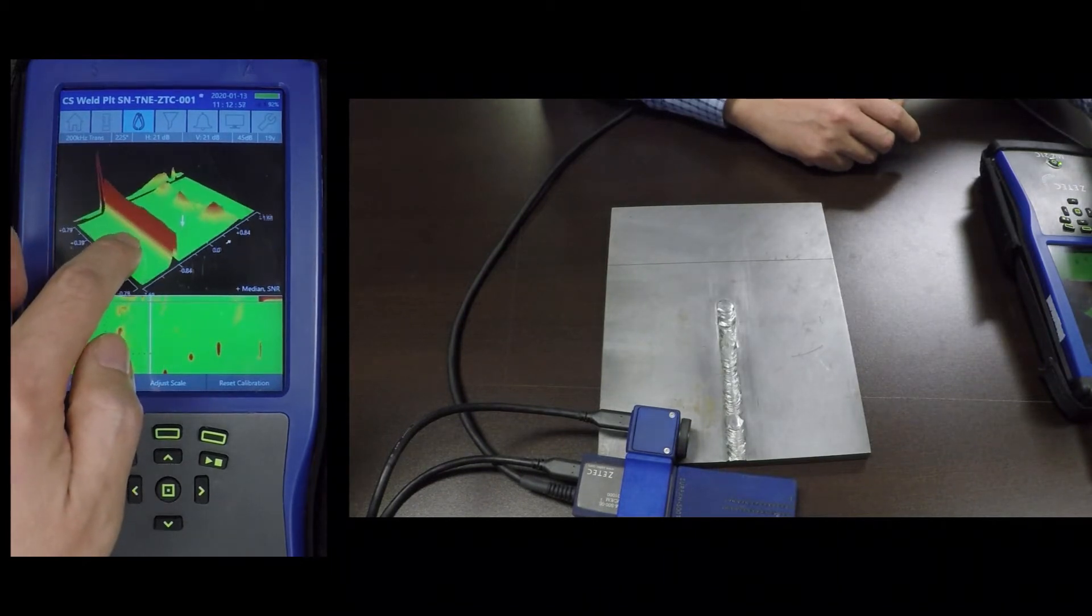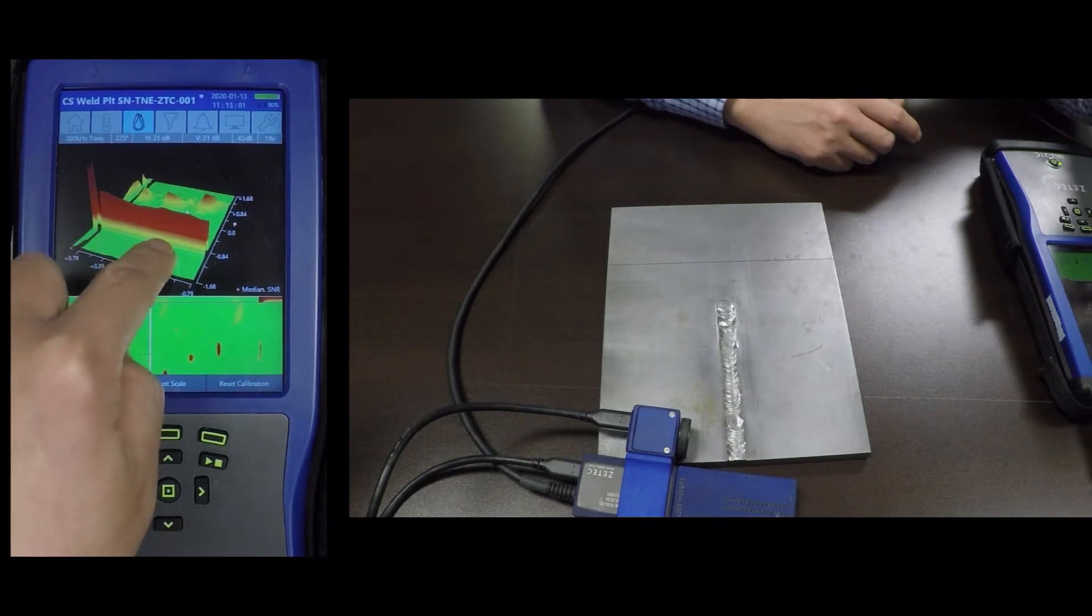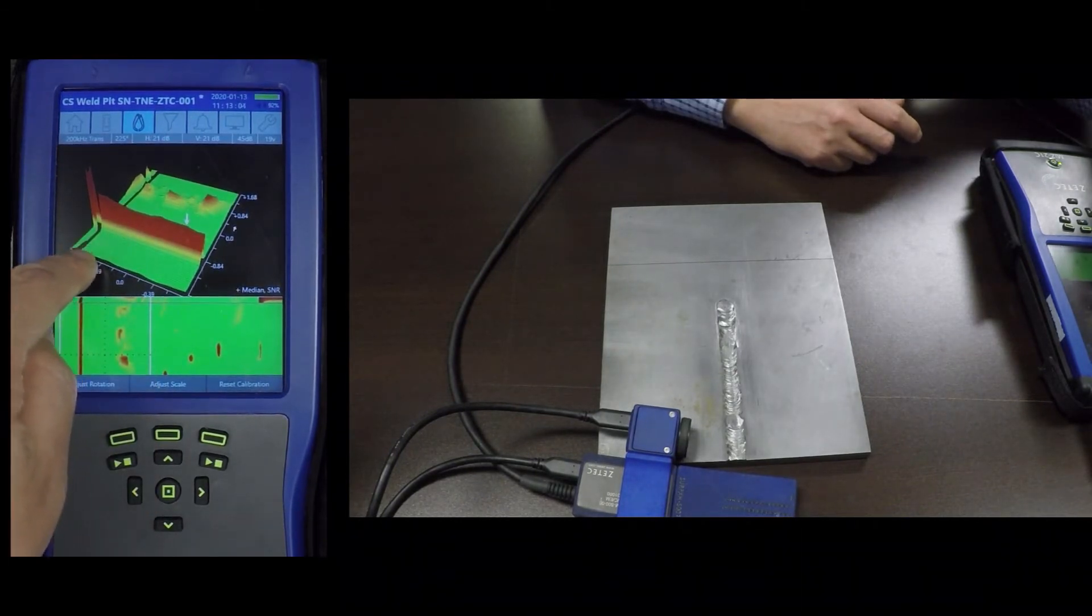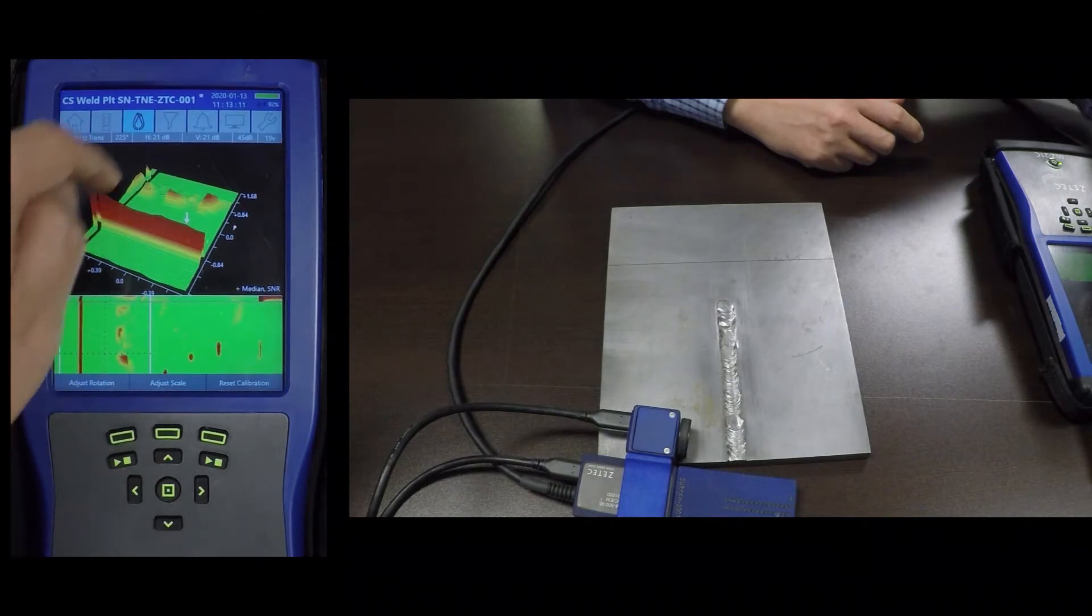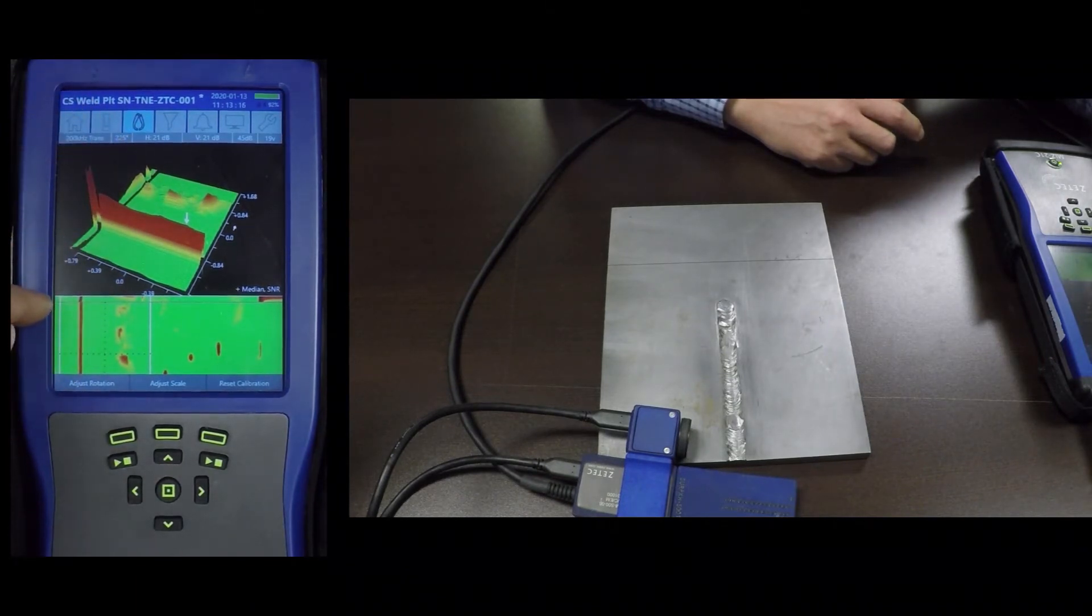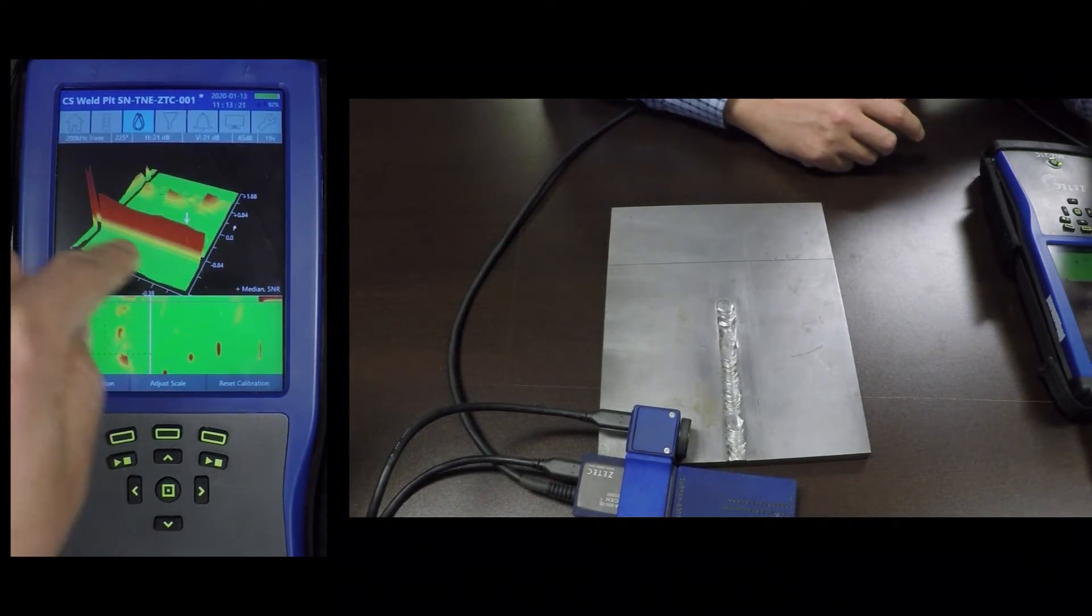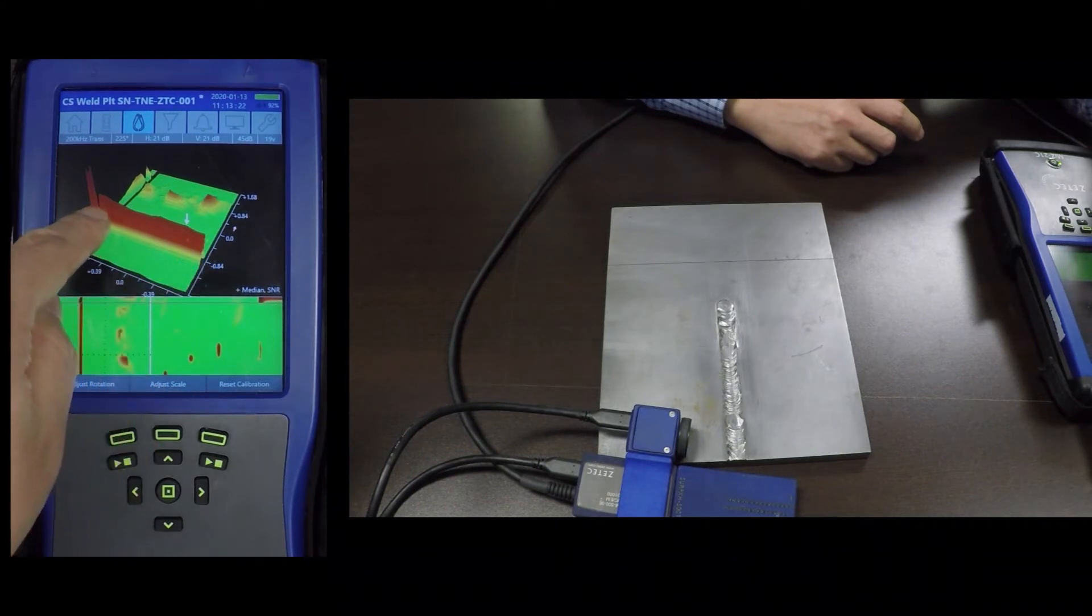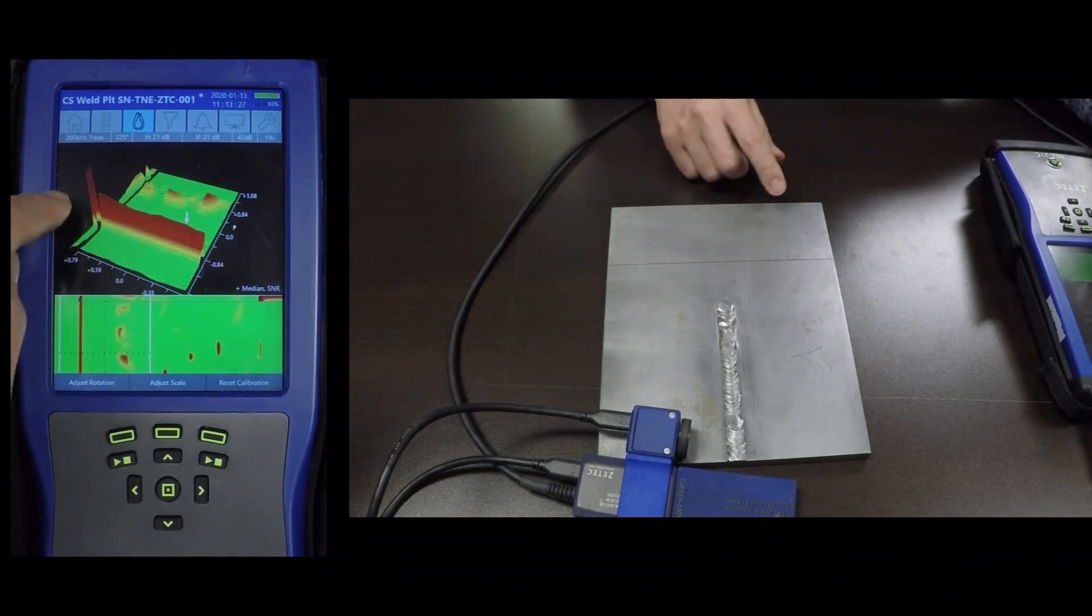So this is my groove. You can see this is the way this is laid out. You have the array coils down in this bottom part of the strip chart. And then this top portion where you see the little gap there, the top portion is your plus point coils. So you can see my array coils are detecting this transverse groove as well as my plus point coils there.